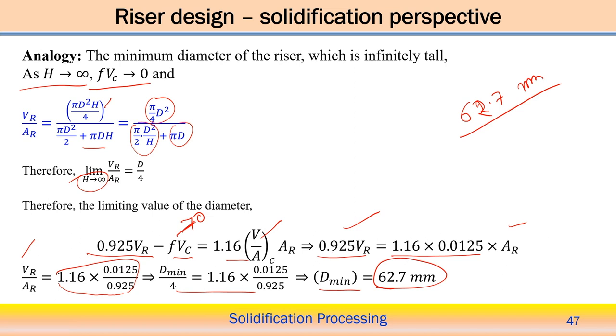So this way we can analyze this and find the optimum value of the diameter. At the same time, for an infinitely long cylinder, we can also estimate the limiting minimum values of the diameter using a similar expression, and estimate the minimum values of the diameter for the top cylindrical riser and side cylindrical riser. I think that is all.